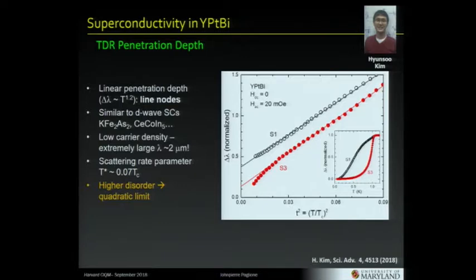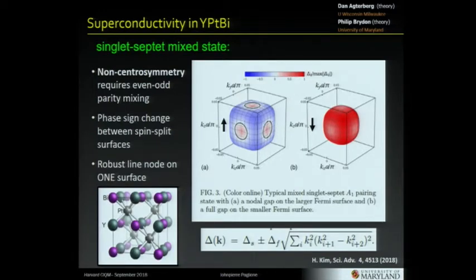by this technique, it shows nothing that goes beyond sort of quadratic behavior in the temperature, which is consistent with a superconductor that has intrinsic line nodes, where if you put in more and more disorder, it doesn't destroy the nodes. They're not accidental. They remain, and it just changes the temperature dependence a little bit from linear to quadratic. If it keeps going higher and higher, then you likely have some accidental nodes, and it's actually a fully gapped superconductor. So that's consistent with a true intrinsic nodal superconductor.